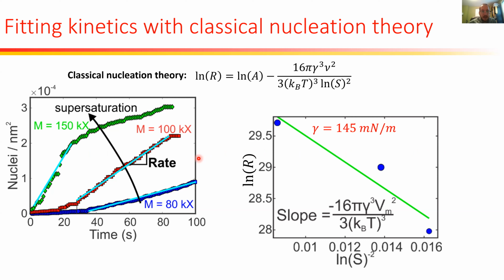How long did it take nucleation to complete? Well, you can actually see it in the red plot, right? It goes flat right here. So about 80 seconds is when we stop seeing new particles. And that happens for two reasons. We fill up all the nucleation sites, basically. And then it becomes more favorable for silver atoms to just add to existing nanocrystals instead of nucleating. So the path of least resistance changes, right?